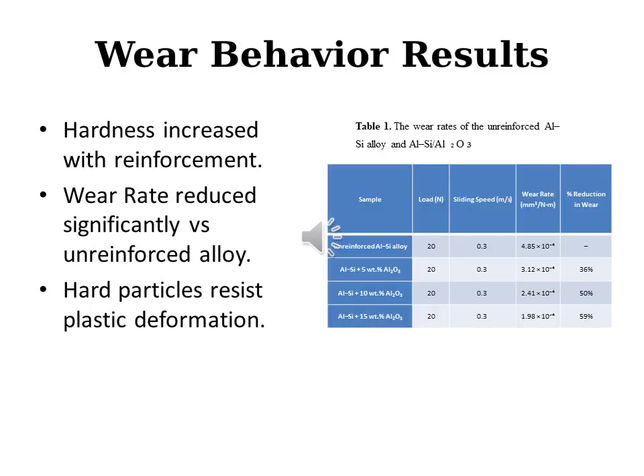In slide 6, wear behavior results. Regarding wear behavior, the hardness increased with the addition of reinforcement. As you can see in the data, the hard ceramic particles resist plastic deformation when comparing the unreinforced alloy to the composite. The wear rate was reduced significantly. For example, adding 15% alumina reduced wear by 59% compared to the unreinforced alloy. The specific wear rate dropped from 4.85 to 1.98 times 10 to the power of -4.